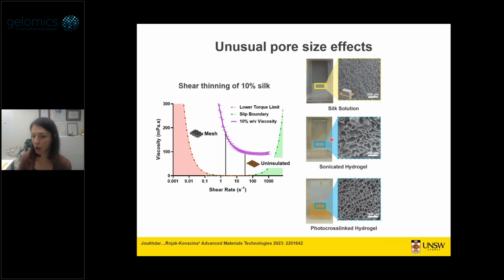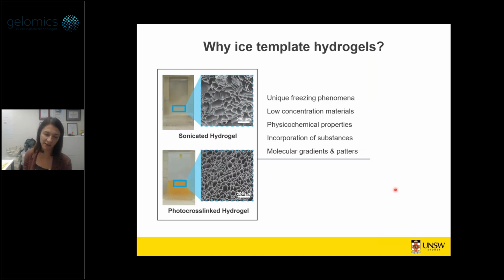However, if we now take our cross-linked silk, whether through beta sheet or through dityrosine bonds, and now freeze it, we get very large pores, very high resolution pores, because we have now again artificially introduced this viscosity, in inverted commas, into silk, right? And so this dityrosine cross-linking is also allowing us to ask these fundamental questions about the freezing processes and thermodynamics and the interface between that and material properties, which I think is really exciting.